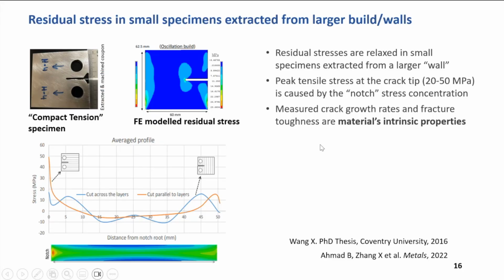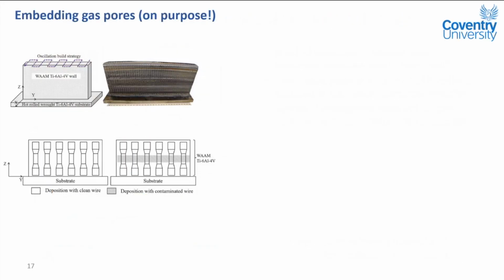So the material properties I present today can be regarded as intrinsic properties, only reflecting the additive manufactured materials' microstructure effect and the porosity effect. So with that, I just have one slide to show. We also, in the methodology, probably were the first people about 10 years ago to embed gas pores on purpose.